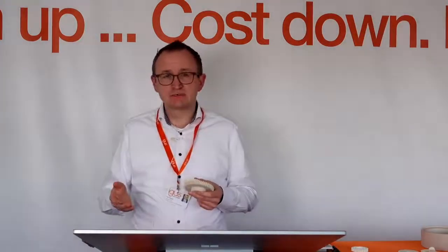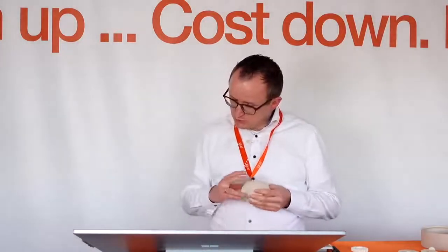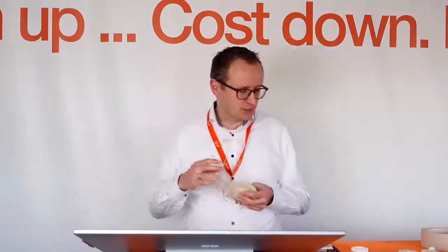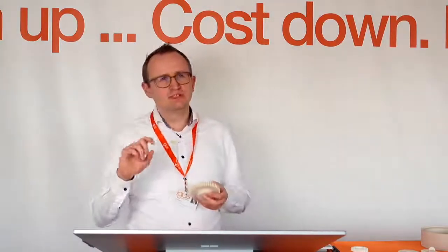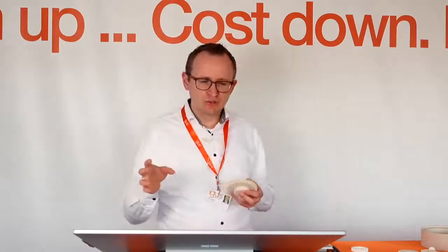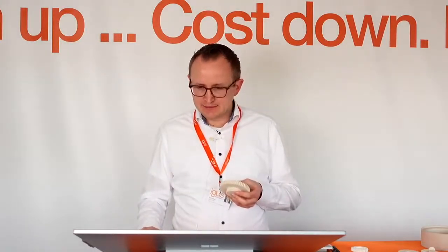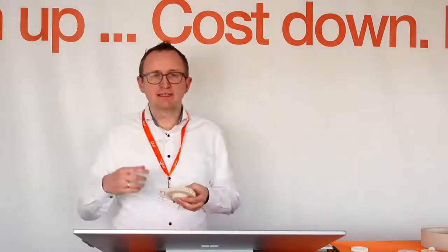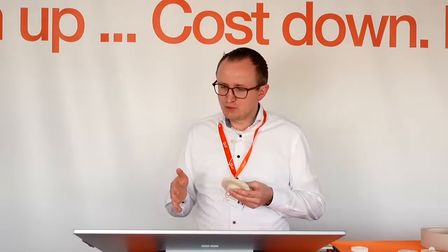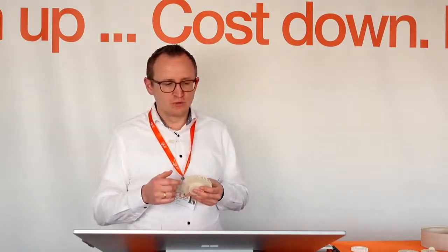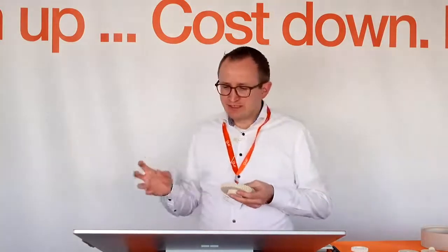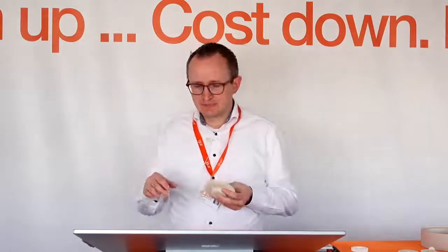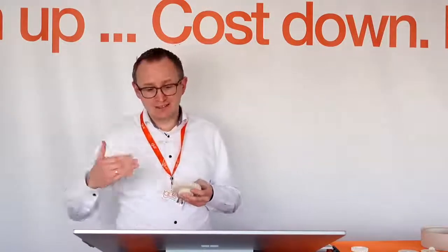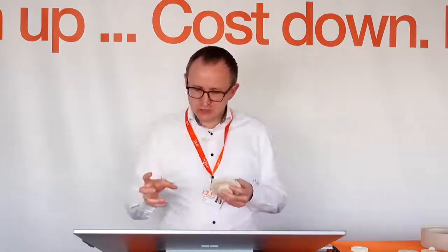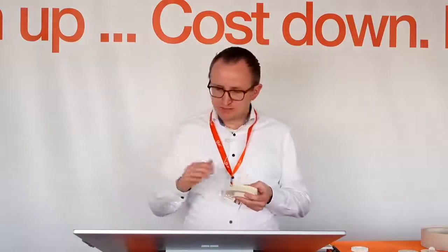Another question about small sizes: how small can we make worms and worm gears? Our minimum wall thickness is about 0.7 millimeters. We can also go down to 0.5. For worm gear drives especially, we had a higher lifetime than with a regular machined worm gear. The running partner, the worm shaft, was anodized aluminum. If you have a high load on the worm gear drive, the worm shaft needs to be metallic. If you don't have such a high load, both parts can be plastic.